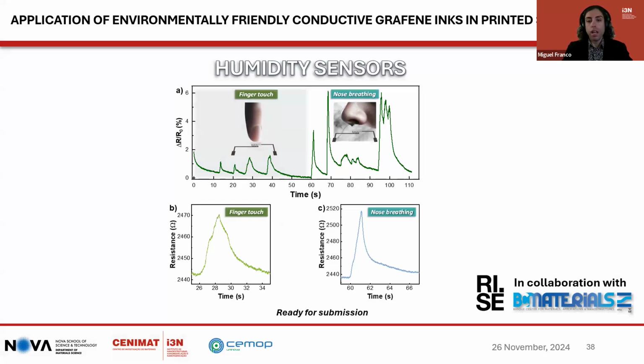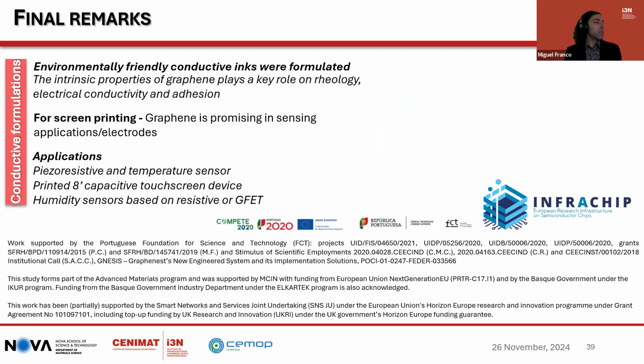Also, these sensors have a quick response time, up to 5 seconds, that can be used to detect nose breathing or even the touch of a finger. This device is also robust and can withstand cycles. As final remarks, there is an environmentally friendly formulation, linked to key properties of graphene that play a key role in rheology, electrical conductivity and adhesion. For screen printing, graphene is promising for sensing applications and electrodes, and piezoresistivity and temperature sensors were developed. We also developed printed 8-inch capacitive touchscreen devices and humidity sensors.